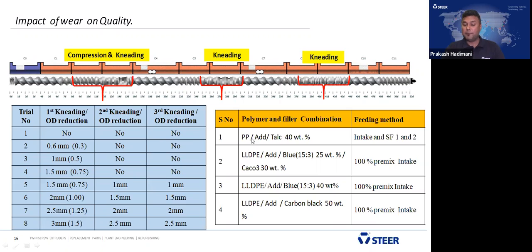We have selected the first application, polypropylene with 40% talc. We use the split feed method, meaning polymer is fed from the intake and the remaining talc is fed from each side: side feeder 1 and side feeder 2. And LLDPE with blue pigment 15:3, 25%, plus 30% CaCO3.